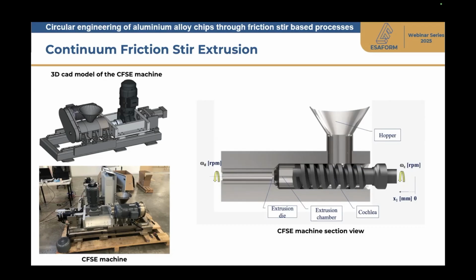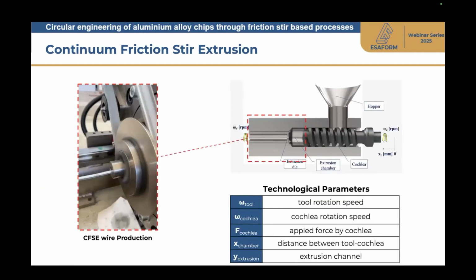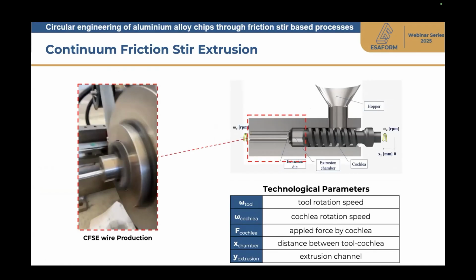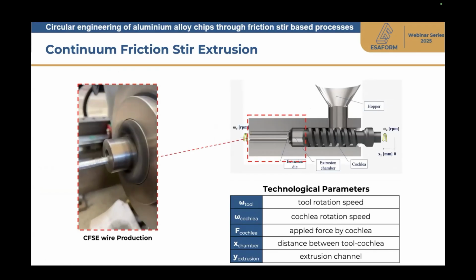And in this way, the actual extrusion occurs, and theoretically, a fully continuous process could be obtained. Actually, it should be observed that the addition of chips has to be well done and definitely continuous and stable in order to let the process be really stable and continuous. Should be observed that, as you can see, it works. I mean, it works. It is complex. It is sometimes unstable, but actually it works.